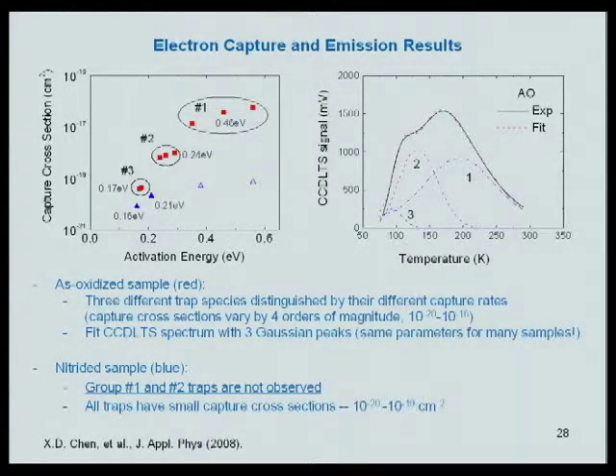The other key thing here is that the remaining traps have very small capture cross-sections. The traps that are left at the silicon interface have capture cross-sections that would be up here on this plot. So the actual interface defects that are left in silicon carbide are quite different from what would be seen in SiO2 on silicon.